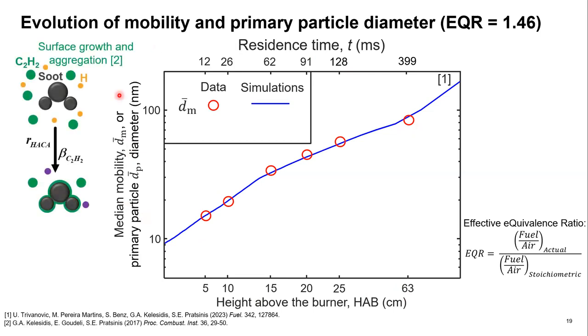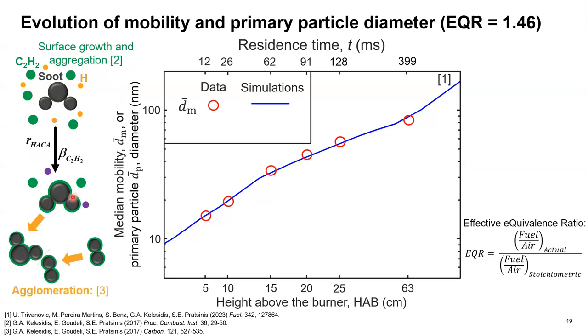Basically, how these discrete element models work is we have soot, which we assume is growing through the hydrogen abstraction carbon addition mechanism, or the HACA mechanism. Here, acetylene reacts with the surface of soot and grows the size of the particles through surface growth. At the same time, the model is tracking how the particles flow through the system, and when the particles bump into one another, we assume that they agglomerate together. At the same time, because surface growth is continuing to occur, these particles can go from agglomerates into aggregates because the surface growth forms necks and hard bonds between the otherwise weak point contact bonds.